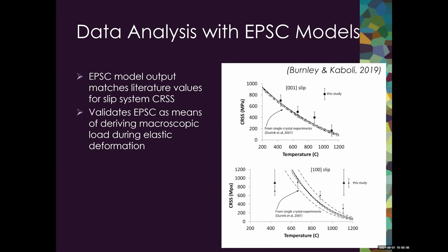This data basically just shows that the EPSC model output is matching the literature values for the critically resolved shear stress for slip systems in olivine. And this just gives us further confidence in our EPSC modeling strategy.